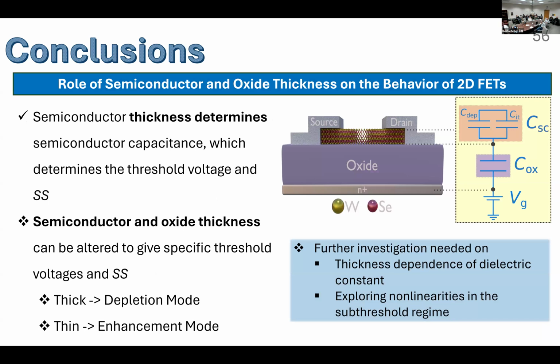For my second project, where I looked at the role of the semiconductor and oxide thickness on the behavior of 2D field effect transistors, we saw that the semiconductor thickness determines the semiconductor capacitance, which then determines the threshold voltage and the subthreshold swing. We can manipulate the semiconductor and oxide thicknesses to give us different values of threshold voltage and subthreshold swing. So for example, there are two main modes for MOSFETs. We have the depletion mode, in which you typically need to apply a gate voltage to turn the device off. And then we have enhancement mode, in which the device is typically off and you need to apply a gate voltage to turn it on. So simply by changing the thicknesses of our materials, we can go into either a depletion mode FET or an enhancement mode FET.